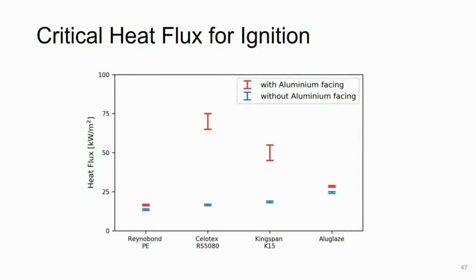I performed a range of experiments to characterize the ignition behavior of the 4 products of interest, some of the key outcomes of which are summarized in this plot. On the vertical axis in this slide, I'm plotting the heat flux, again, the severity or intensity of heating in kilowatts per meter squared. Now, to put those values in context for you from 0 to 100 kilowatts per square meter, at the low end, exposure to a heat flux of 5 to 10 kilowatts per square meter is likely to result in skin burns in less than about 30 seconds.